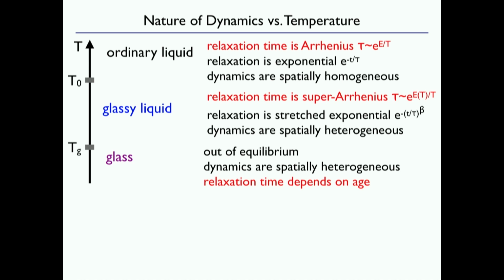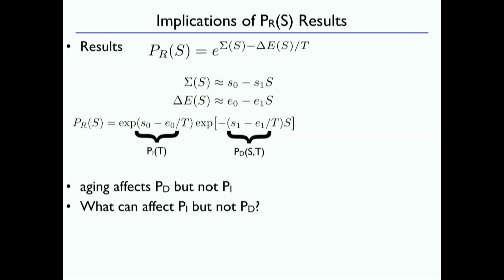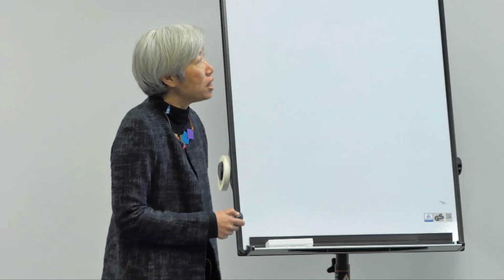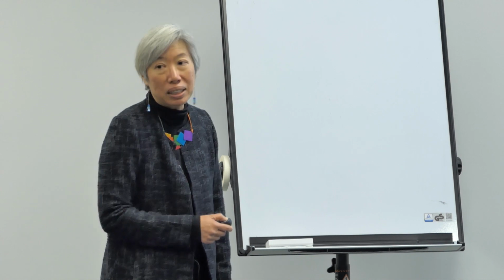Relaxation time is Arrhenius above the glass transition, where softness doesn't matter. Then it starts to depend on softness. It becomes super Arrhenius. Below the glass transition it depends on the age, and we understand how it depends on age. So now let's think about this a bit. I have the softness independent piece, and I have the softness dependent piece.